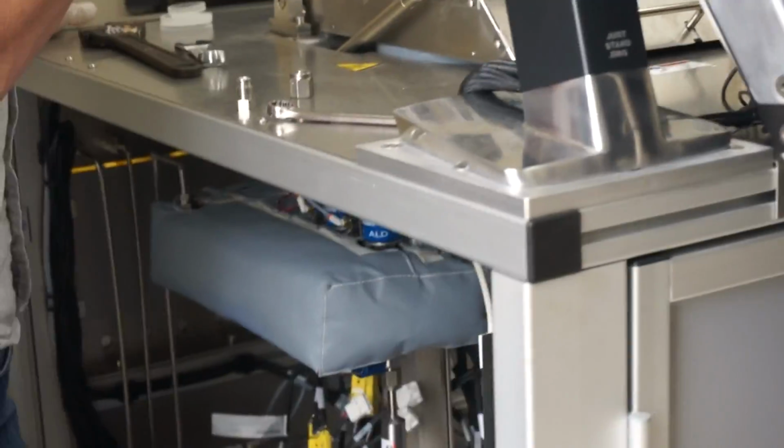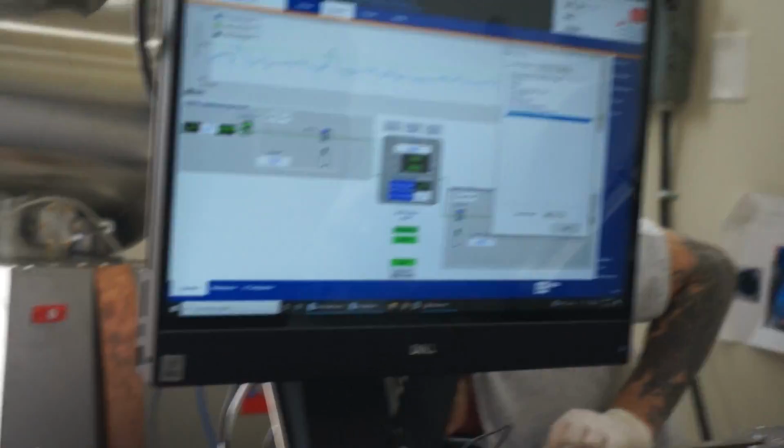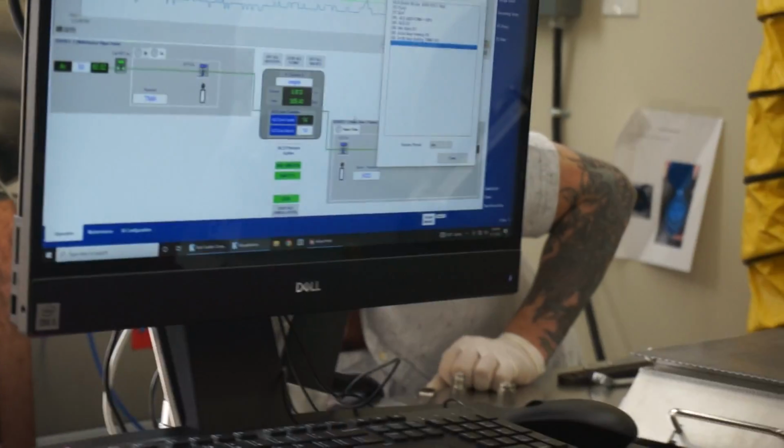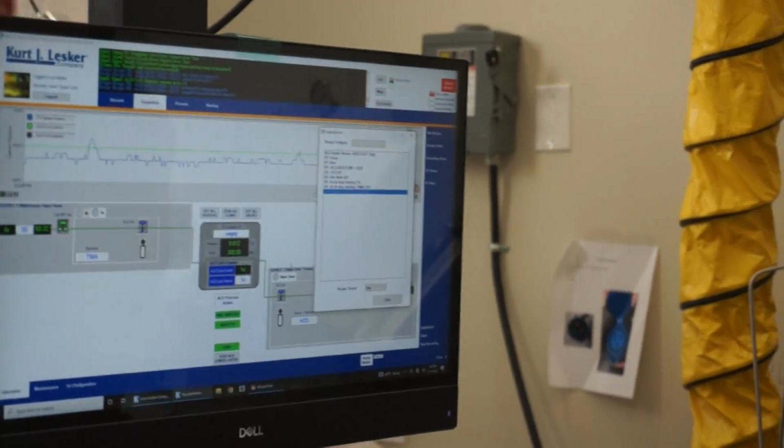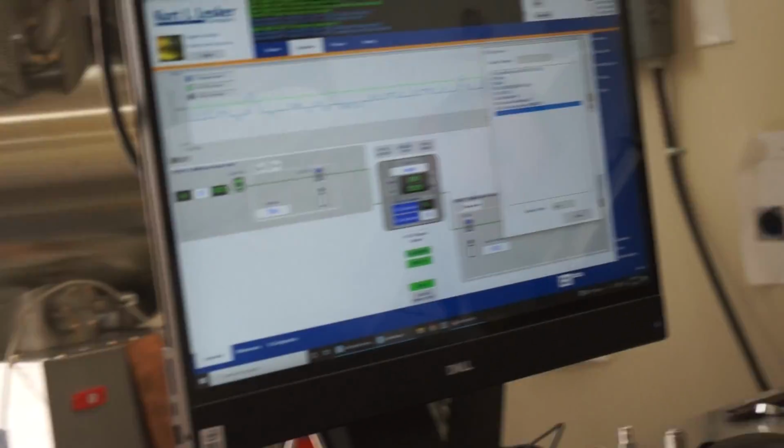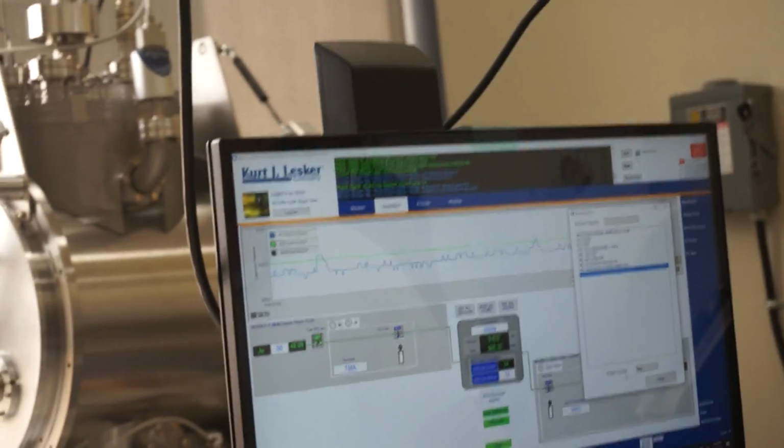Some people do, but then eventually what you can get is a little bit of buildup on the seat of the ALD valve. Then your precursor leaks out into the process, and if it leaks enough, then you wasted $1,500. Now I'm going to open the manual valve on the TMA, which is a little bit warm. H2O is closed. Again, tomorrow I should have a conditioning recipe.